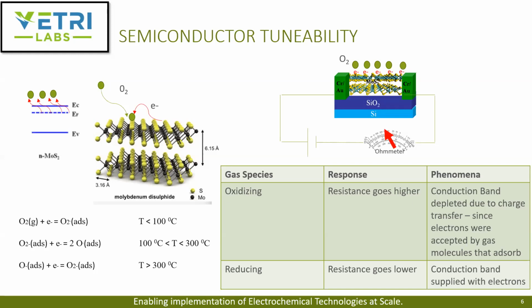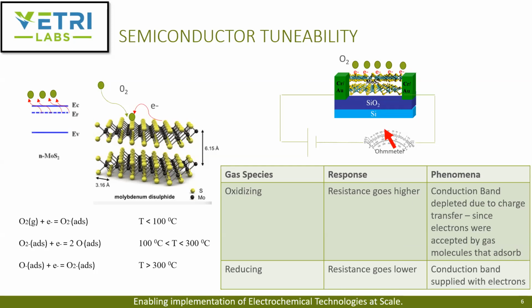If you have a circuit, apply a voltage and measure current or resistance, you would see that as the conduction band is depleted, the resistance of the material goes up and the current should drop. If there's a reducing gas, the opposite will happen. The conduction band gets supplied with a lot of electrons, and that gives more current through the device, and the resistance goes lower because there are more electrons in the conduction band. Typically, this is the principle of operation.